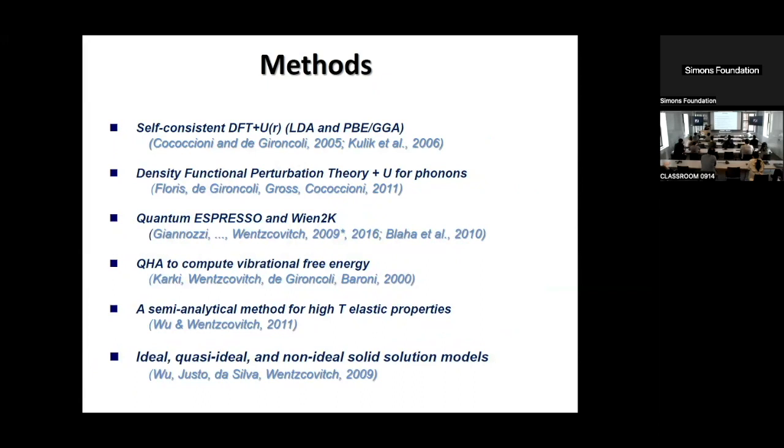Where you see LDA, I've used LDA plus U, which gives some of the best structural properties, better than LDA-only, SCAN, or R2SCAN, that meta-GGA kind. So where you read LDA, you might think today you would redo this with a meta-GGA.